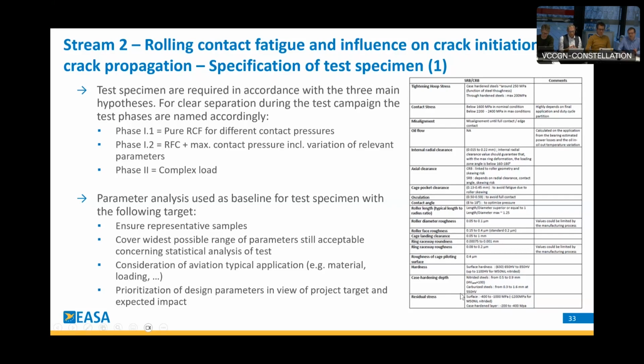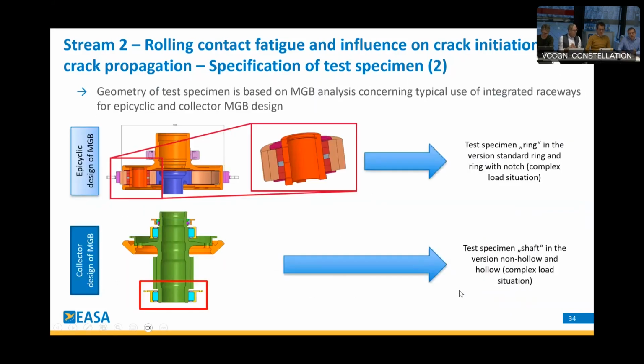So this was the baseline, of course, only on the micro level. We talk about contact stresses, about micrometers, we talk about stresses in the part, but we need, of course, also to look at the macro level to have a representative sample. And therefore, we made it quite easy. We looked at the MGB analysis, of course, done in Stream 1, for example, and we looked at where we have the integrated raceways typically.